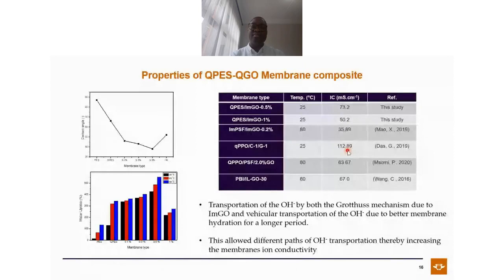We're saying this membrane system has transportation of the OH minus by both the Grotthuss mechanism, which is a hopping method, due to imidazole graphene oxide, and vehicular transportation due to better membrane hydration for a longer period of time. This allowed different paths of OH minus transportation, thereby increasing the membrane conductivity. All of this is due to the imidazole functionalized graphene oxide, because we also did one without graphene oxide. As you can see on the water uptake, this section is the one without graphene oxide. You can see it's the lowest in terms of uptake. But the moment you add graphene oxide, you can see that the trend goes up, which means graphene oxide is actually working.